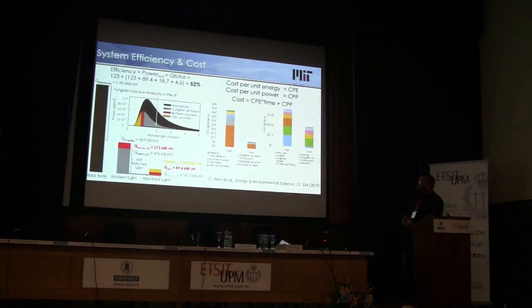So here's a very rough picture, a simple set of estimates to try to convince you that we think we can get to about 50% efficiency. We pay a very significant penalty using the tungsten. So black body radiation at nominally, this is at the intermediate temperature for us, 2150 C, halfway between 1900 and 2400. And you get a lot of black body radiation in theory. It's almost 2 megawatts a square meter.